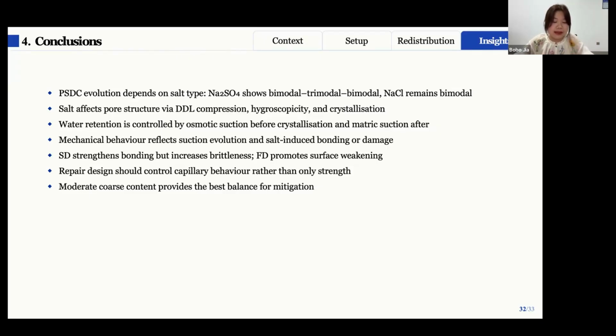From an application point of view, this means that simply matching the original soil or increasing strength is not enough. Instead, we need to control how water and salt move through the material. This is where the capillary barrier concept becomes useful. By adjusting the pore structure, especially through grain size design, we can regulate the water and salt transport and reduce the risk of salt damage. So overall, the key message is that controlling capillary behavior is essential for designing more durable repair materials.